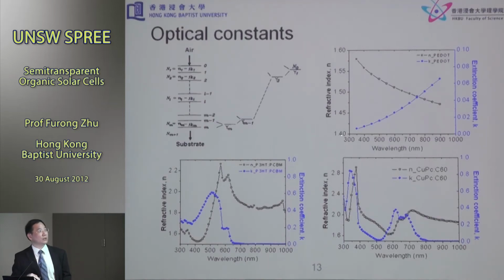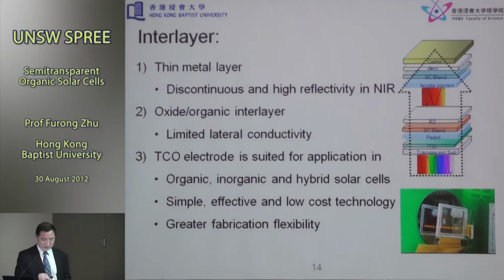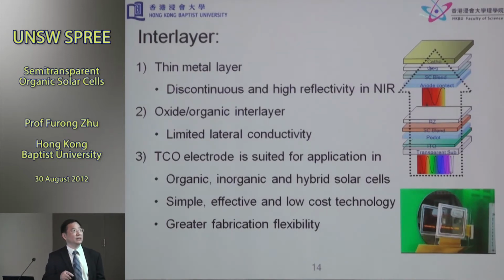So in this work, the first thing you need to do is to get the N and K values of the blend layers, and all the layers, which you can measure, and then use this as a basis so you can calculate the light propagation in the systems. Okay, and as I mentioned, for organic semiconductors, one of the limitations is that the absorption profile is narrow. So in order to have high efficiency solar cells, one approach is to stack them together to form a tandem solar cell. So you have subcells which respond to different parts of the solar spectrum, and then you stack them together. So the entire stacked cell becomes responsive to light in a broader range.